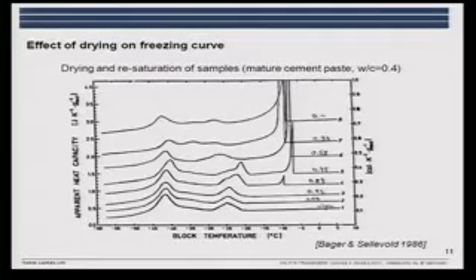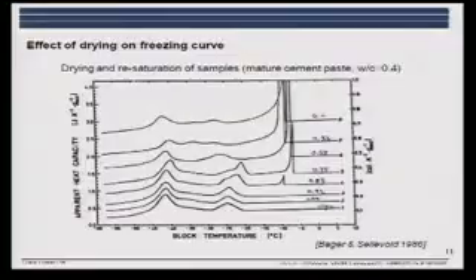This is another technique, and this is data for low temperature calorimetry, where you have a saturated sample, and you subject it to cooling, and at a certain time there will be ice formation in the sample, and then you are measuring the heat development due to the ice formation. And the smaller the pores, the lower the temperature when you will see this heat development. So this is an indication of the pore structure.